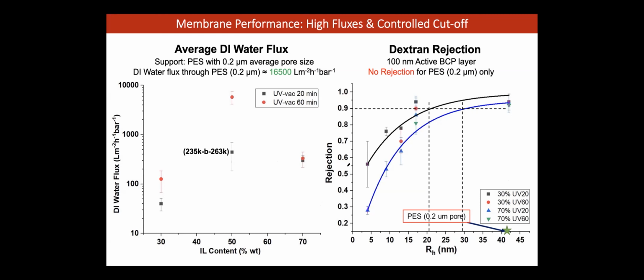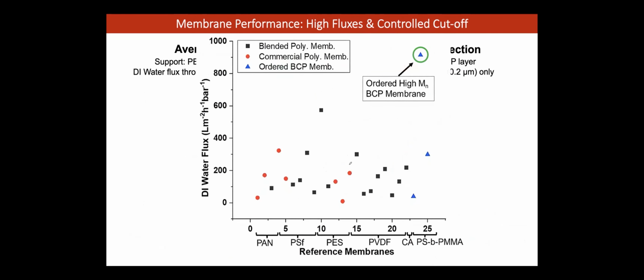So you have to think about, is rejection most important to you or is it the flux? This goes back to the age-old prediction, the Robeson's law, which is that flux and rejection are inversely coupled. You can have high flux, low rejection, and vice versa. So the next big challenge is how to get high rejection and high flux. But again, I think block copolymers actually offer the solution. And here's the reason why I think so.